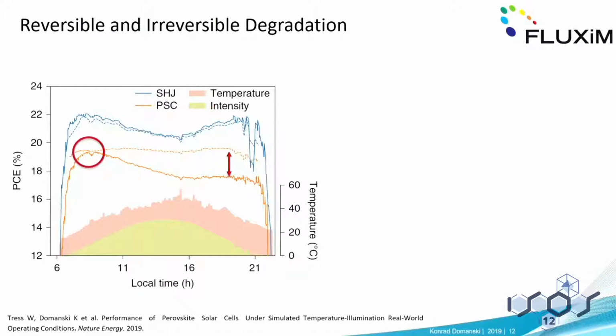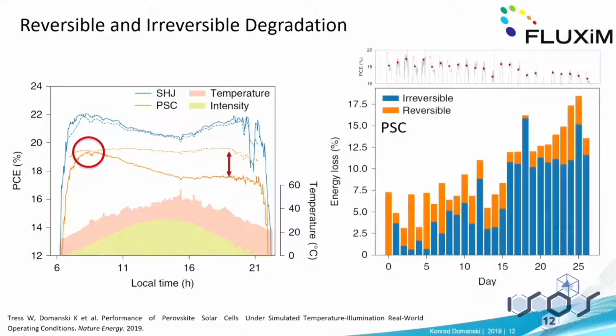But there is always, at some point of a day, a point where we get pretty close, or closest, to the predicted efficiency. And what we did, we looked at this point every day and quantified how much of the degradation is recovered and how much is actually permanent. So this is how the result looks. The orange is reversible degradation, the blue is irreversible, and we see that for the perovskite device, we consistently accumulate the irreversible degradation.